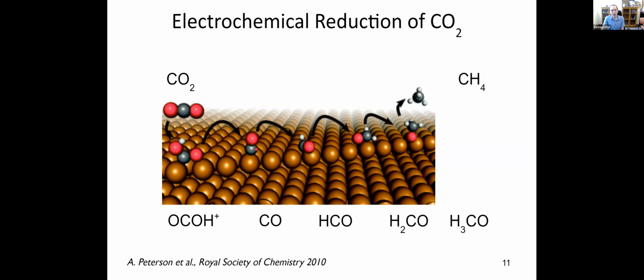There's other competing pathways. This is a super oversimplified picture. But what's really interesting about this is when you do these sort of microkinetic models, you can sort of identify the steps that are most challenging. And in this specific pathway, the step that is most complicated, most difficult to happen on the copper surface is taking the CO molecule and adding this first hydrogen. The CO to CHO step is generally considered to be the rate limiting step on a copper surface. You can do explicit nudged elastic band calculations to try and find the transition state between these two. When you do that, what you find is that the transition state looks a lot like a partial desorption of the CO molecule. And so a descriptor that's very helpful for CO2 reduction is what is the binding energy of the CO molecule sitting on a surface. I'm going to come back to that in a second.